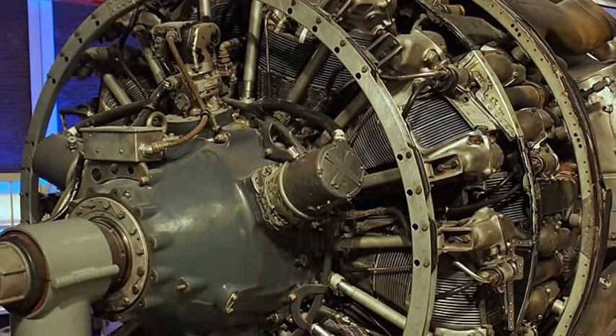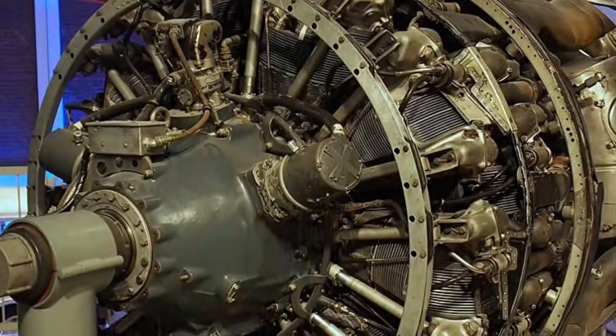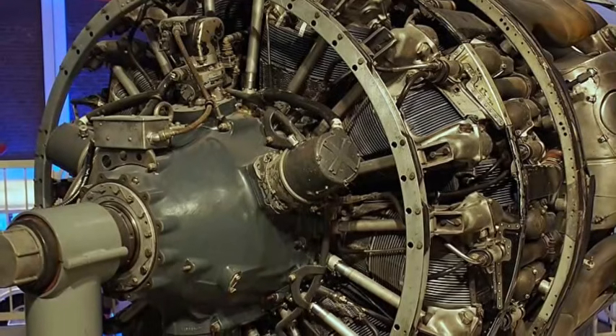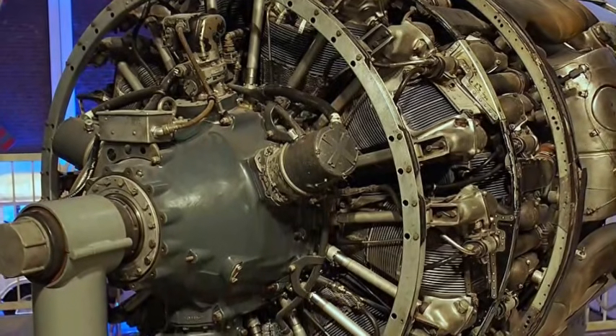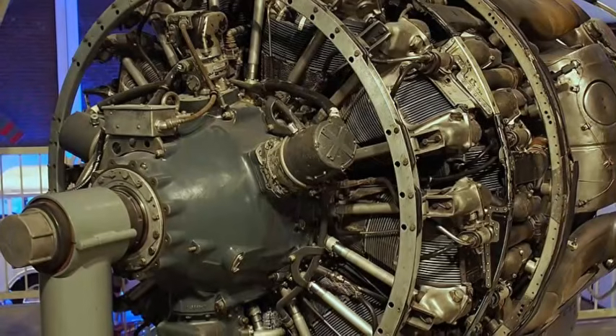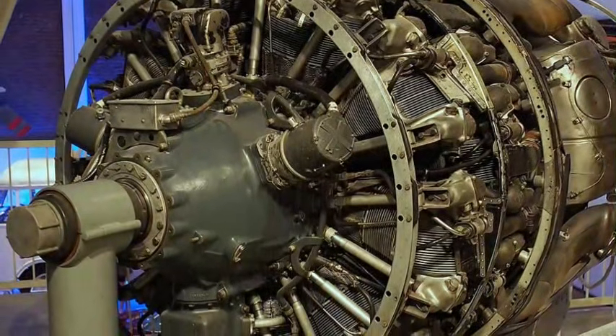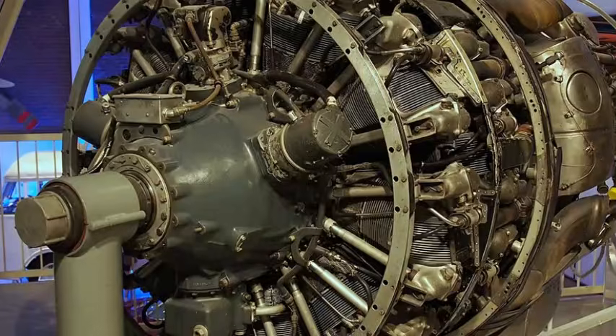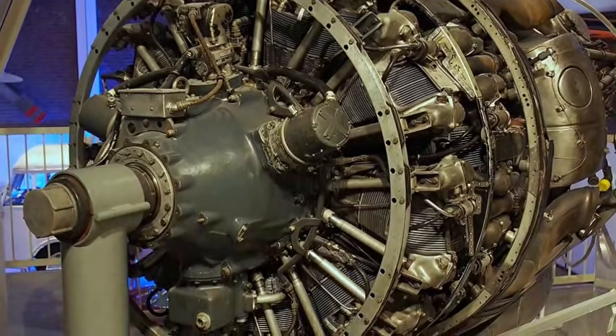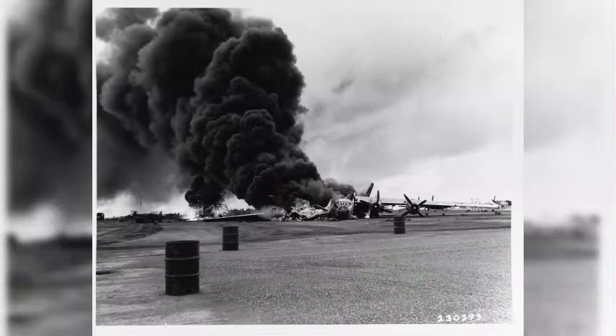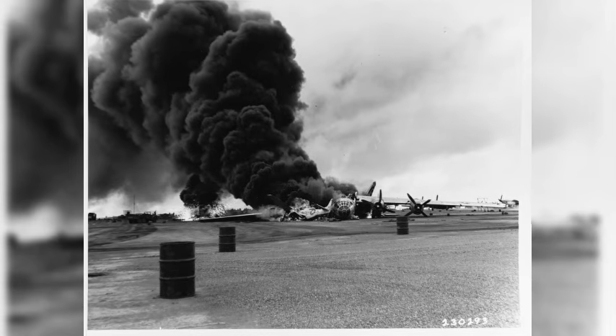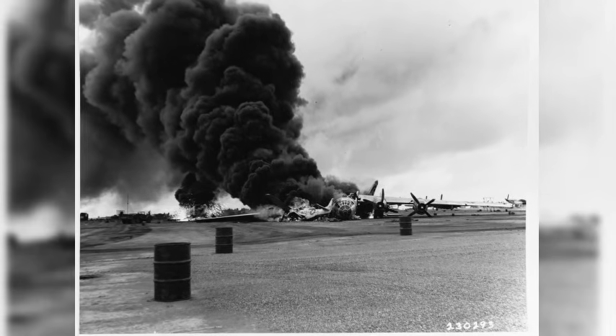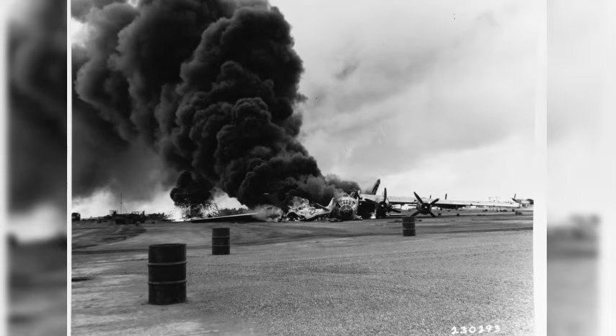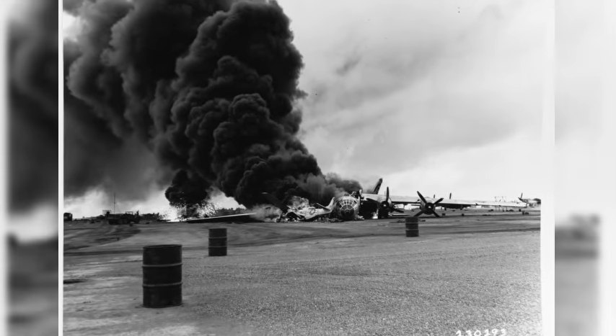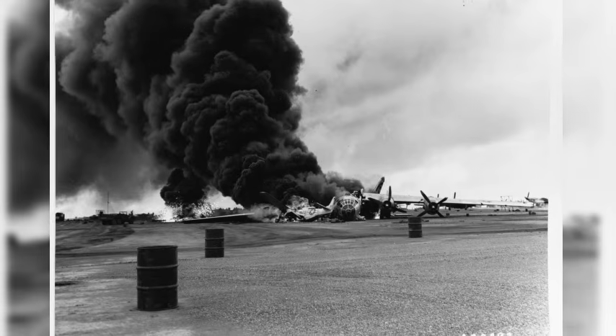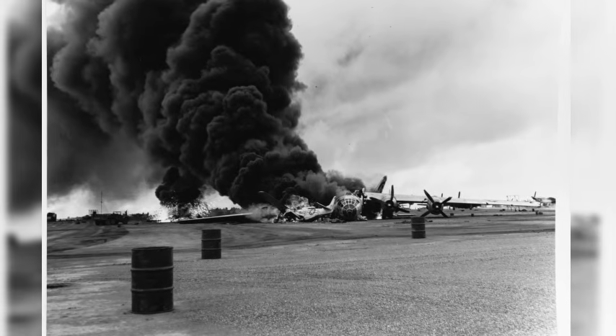By 1943, the B-29 was flying with R-3350 engines, and the engines remained temperamental, with the rear cylinders tending to overheat badly, partly because of inadequate clearance between the cylinder baffles and the cowling. The R-3350's overheating problem was the defining flaw of the early B-29 program, and it was directly connected to the spark plug problem, because heat was the enemy of both the engine and the plugs.